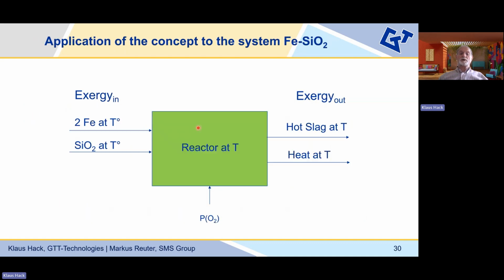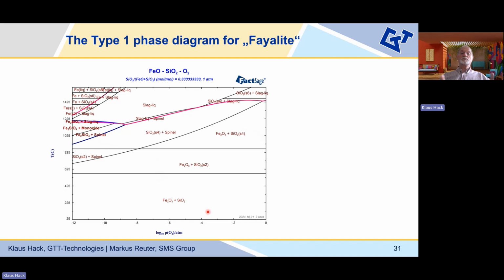particular oxygen partial pressure. So really, our simple view of the process would be this. We put iron and silica in. We can calculate an exergy for these. We can get hot slag out and also heat, but we don't know how much heat yet because we don't know how much oxygen yet. We only know the oxygen partial pressure. So in that case, we have to first look at our phase diagram with respect to oxygen partial pressure.